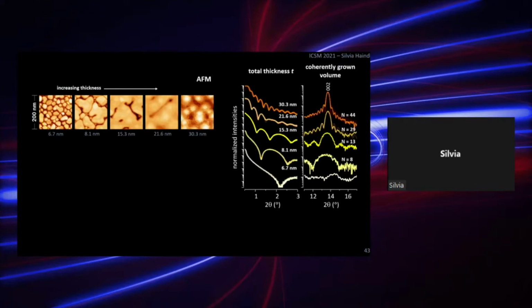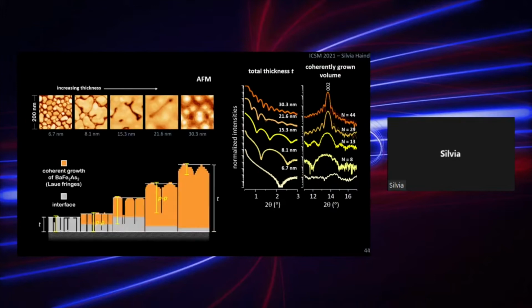So here are the thicknesses as determined by the X-ray reflectivity. This is the total thickness by the X-ray reflectivity. However, we can also determine the coherently grown volume by the Laue fringes. When doing so, we can map the situation in a sketchy graph. And what we find here, and what you can see here, is that in all the films we have a part of an interface layer which is not coherently grown barium 122.